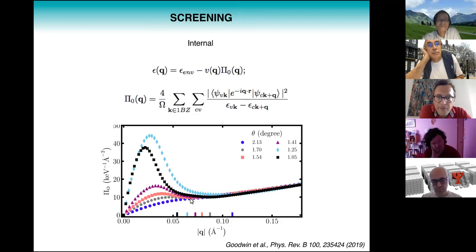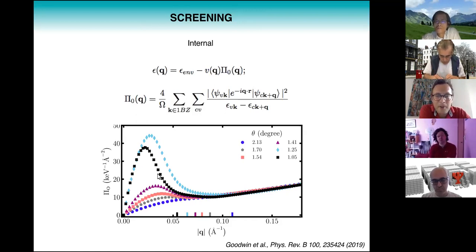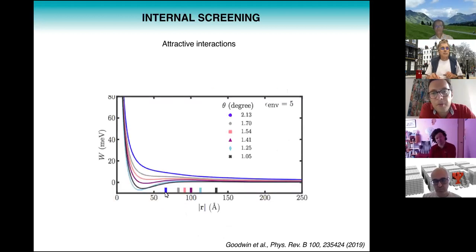You see, if you're far from the magic angle, you get something that's more or less linear, which is precisely what you would expect from graphene. But as you approach the magic angle, you get a very pronounced bump. This bump is of course just a reflection of the renormalization of the Fermi velocity close to the magic angle. So this gives us the polarizability and then also the dielectric constant. And from the dielectric constant, I can calculate the screened interaction. Here I'm showing you the screened interaction as a function of position. So this is the screened interaction between 2 electrons.